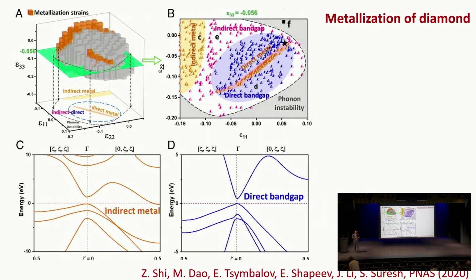Then we created out of this a 3-dimensional space of principal strains, epsilon 11, epsilon 22, and epsilon 33. It essentially tells you the entire map of strains where you can make diamond behave like a metal. So you have direct band gap, you have indirect band gap, and you have the boundary where you get phonon instability, where the structure changes from diamond structure to a graphitization structure. And then if you take a 2D slice at a particular strain, this is a 2-dimensional representation at that particular plane of what the properties are going to be like.